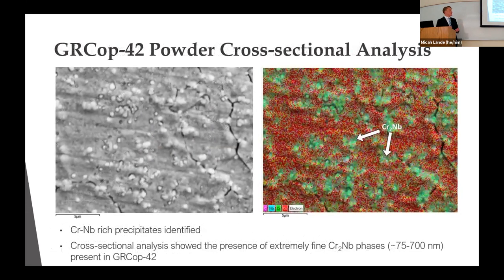And the opposite can be said for GRCop-42, which is less homogeneous. This is the cross-section of a single powder particle, and we can see all these little dots in the green areas here, and that is our secondary phase, our intermetallic phase, that chromium-niobium alloy in there. That leads to it being a dispersion strengthened material, meaning that this will not benefit as much as HR1 from a heat treatment process. But again, these phases are very small. They're very small to begin with at 75 to 700 nanometers, but they're pretty evenly dispersed.